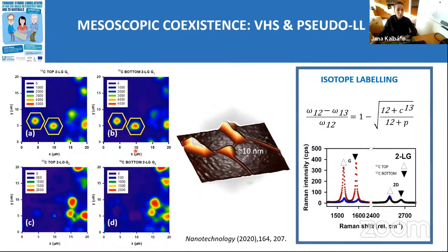And if you look at the map of the Raman intensities in the position of the top layer and the bottom layer, so this corresponds to the carbon-13 and this is the carbon-12, we can find some areas where we see strong enhancement of the Raman signal. And also the shape of the peaks here is different compared to some standard Raman signal from samples of a monolayer, for example. And those features come from the fact that we have a commensurate twist angle between the bottom and top layer.